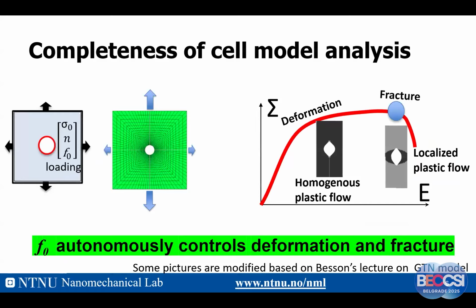So let's talk about the cell model. For ductile fracture, we can easily identify a two-phase cell model. One phase is the matrix material. That we can easily understand. Another phase is empty, nothing. So we have a hole inside. This is a very typical two-phase cell model for ductile fracture. If we make a cell model analysis, that means we can carry out numerical analysis of this cell model. What do we need as input? We need the matrix properties, sigma 0, that's the yield stress, and hardening, n. Sigma 0 and n are the matrix material properties. Then we have F0, that's the initial void volume fraction. That's the only input we need.